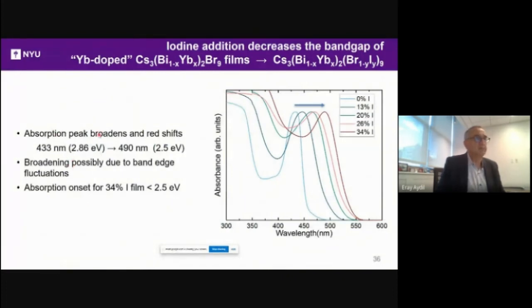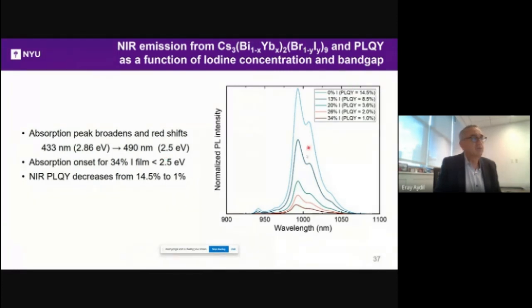As we intended, the absorption peak broadens and redshifts. This is with increasing iodine, going from 0% to 34%. So we're shifting the bandgap, or another way of looking at it is the excitation of the octahedra. The broadening, I think, is due to what are called band edge fluctuations. It's not entirely random, but there is maybe some distribution of bromine and iodine, so the bandgap fluctuates and it's inhomogeneous and widens it. Now, the absorption onset for the 34% iodine film is less than 2.5 electron volts, so you would expect photoluminescence quantum yield to take a dive in the infrared. Indeed, this shows the near-infrared photoluminescence quantum yield. The blue one is the one with the 14.5%. As you go up, by the time you get to 34%, the highest that we could measure was only 1%.